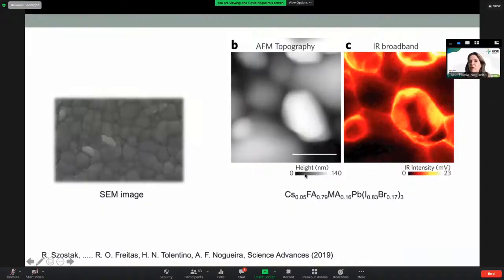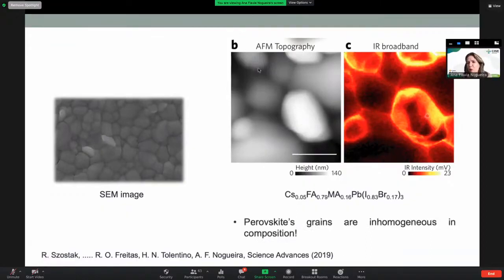So this is what we call an infrared broadband image. Just take one grain here of the perovskite. You can see here that the grains are definitely not homogeneous. Here, when it's much more yellow, you see that there is a depletion of the organic materials in the grains. So now we are looking forward to continue to study this.